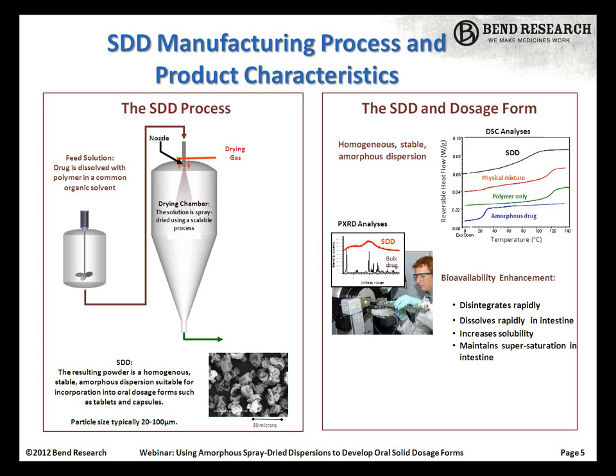As shown on the right there, from DSC analysis you'll get a single glass transition temperature, indicative of a homogeneous amorphous material. The SDDs provide bioavailability enhancement through rapid disintegration, rapid dissolution in the intestines, and an increased solubility. If the dispersion is designed properly, it'll also allow for sustainment of that super amorphous solubility throughout the absorption window.